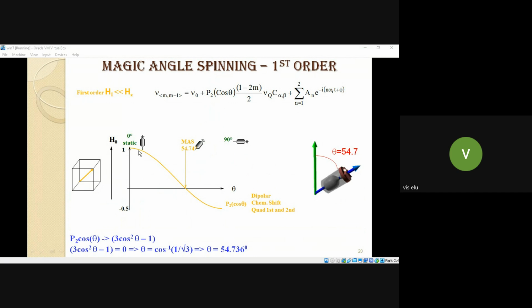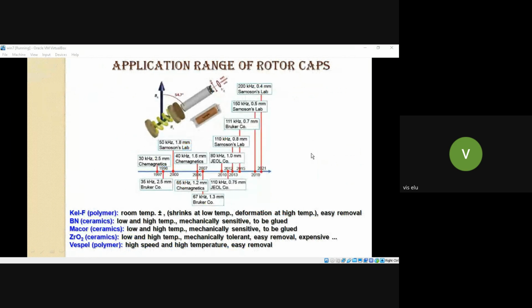You see that in a static case, your sample will be along the z-axis, and you will get a spectrum that is nothing but a broad spectrum. When the magic angle reaches 54.74 degrees, all your chemical shift anisotropy will be removed. If it is a spin-1/2 nucleus, then you will get a sharp line. A sharp line is nothing but the isotropic chemical shift. So your P2 cos theta will become 0 here. And when it moves away, all your interactions like dipolar interaction and chemical shift anisotropy will be reintroduced in the same experiment. So you need to be careful in setting this 54.7 angle. That's a real problem in solid state NMR.